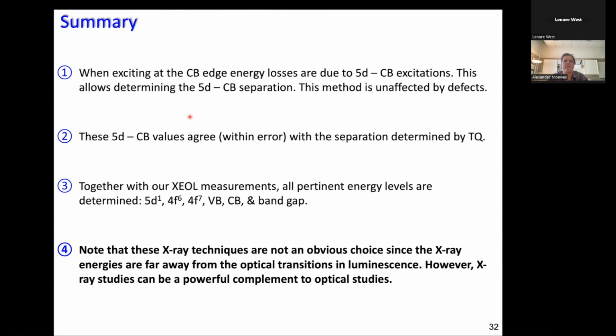Okay, this leads me to my summary. I've shown you that when we're exciting at the conduction band edge, we see energy losses, and we ascribe those to the energy loss when a 5d electron is promoted to the conduction band. And the nifty thing is, because this is done with RIXS, the inelastic scattering method, this is not affected by defects. With an error, these 5d conduction band energies also line up or align with our thermal quenching methods.